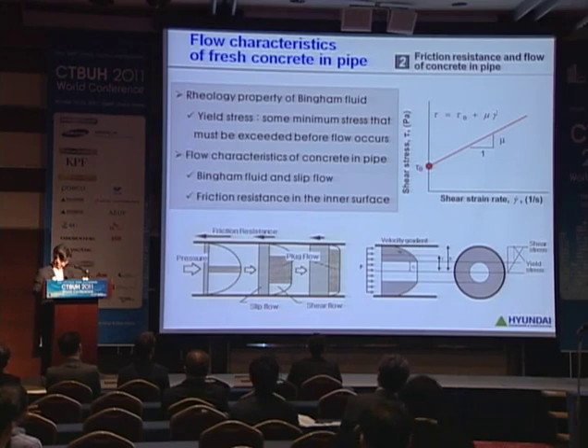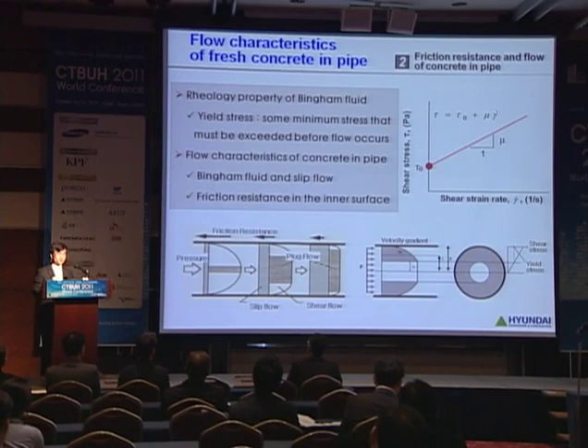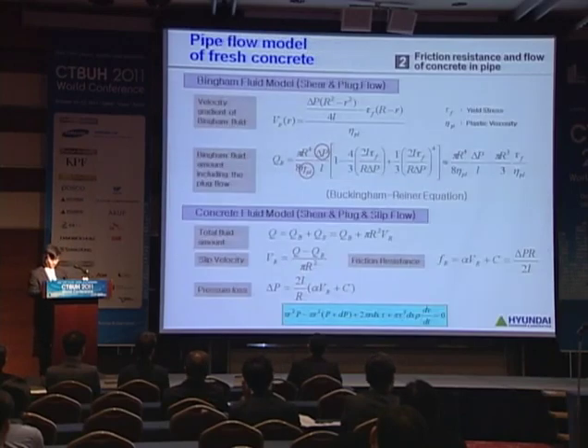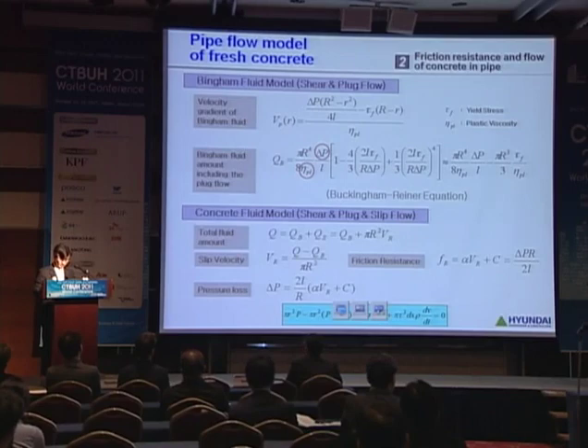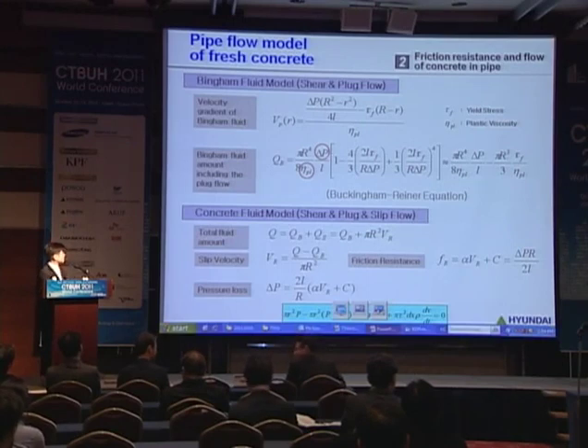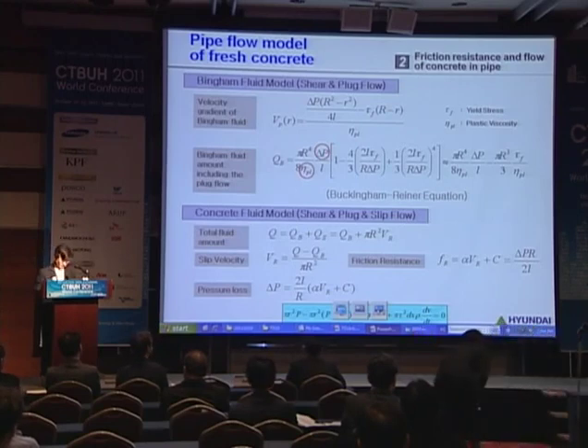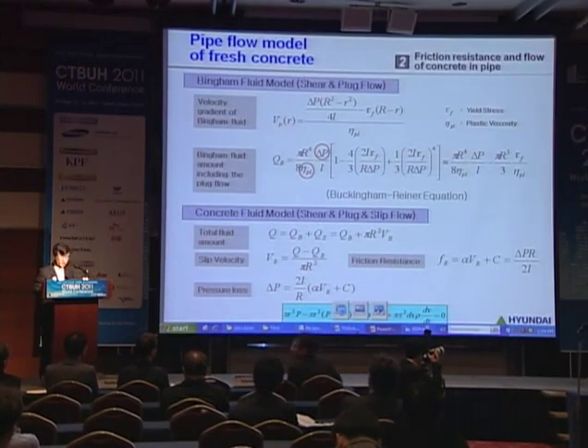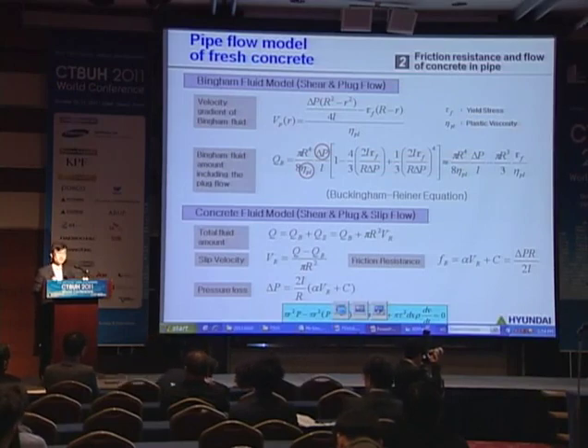Concrete flows inside the pipe by plug flow and slip flow. But when plastic viscosity of concrete is high and inner pressure is high, a shear flow occurs due to the inner friction resistance. This shear flow is called Bingham flow. Bingham fluid amount, including the plug flow, is influenced by plastic viscosity and pressure loss in pipe. As you can see, this is pressure loss in pipe, and this is plastic viscosity. And total fluid amount in pipe is the sum of Bingham fluid and slip flow.